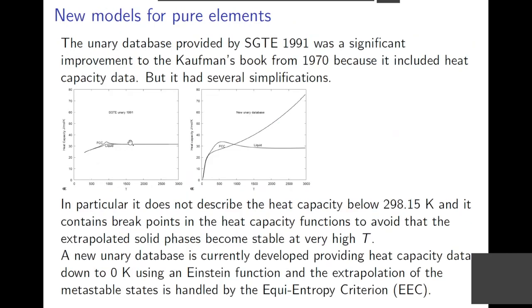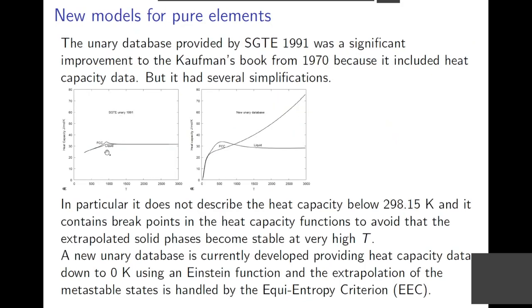So this is pure aluminium in the current unary database from SGTE. In order to avoid that the heat capacity of FCC increases quite drastically before the melting, and to avoid that BCC, FCC aluminium became stable again at high temperature, one introduced a breakpoint at the melting temperature. So the heat capacity of FCC aluminium became the same as the liquid, and the same for the liquid at low temperature approaches the FCC heat capacity.